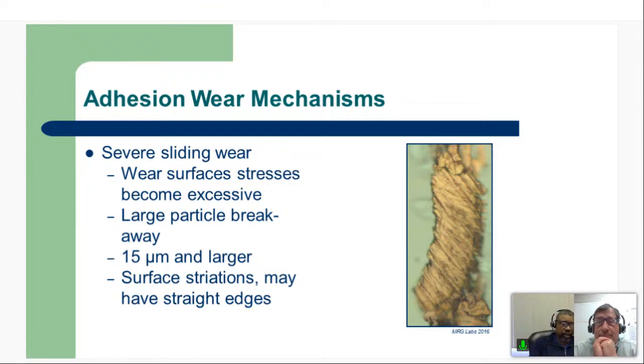And particles in the 8 to 10 microns are nothing. Particles into 200, 300 microns, that's when their cause and effect will come into play for adhesion wear mechanisms for them. So I just wanted to mention that it's application dependent, whereas it's the complete opposite in a turbine world, where you have no touching of anything, and you start seeing particles of 15, 20 microns, that's detrimental to that application. So I just wanted to point that out to people.